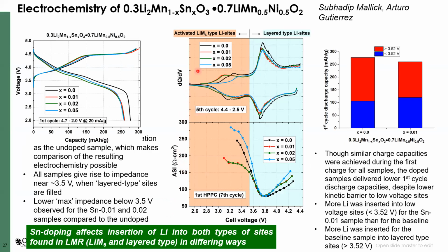So here is the material where we have doped it with a small amount of tin. And as you can see over here, doping with a small amount of tin changes the area-specific impedance at these relatively low voltages. That is the low state of charge regime. So if we want good rate capabilities out of these materials at these voltages, we have to reduce the area-specific impedance to values of this order, around 20 to 40 ohm centimeter square.